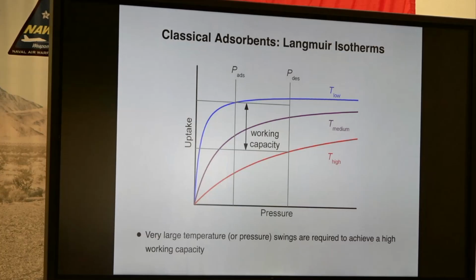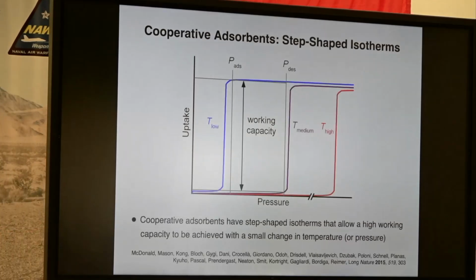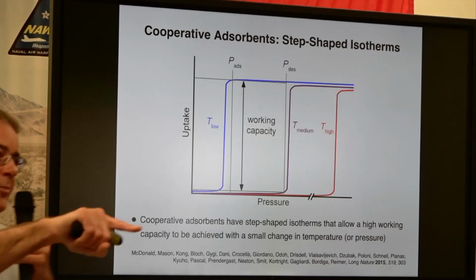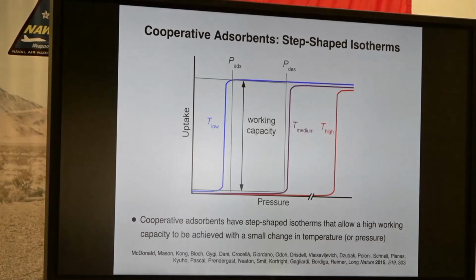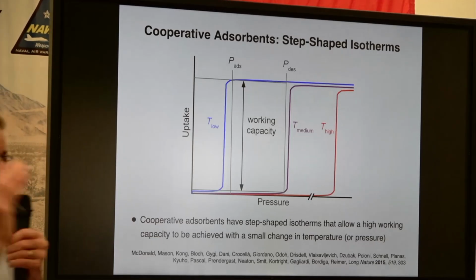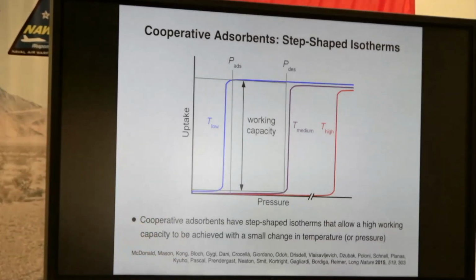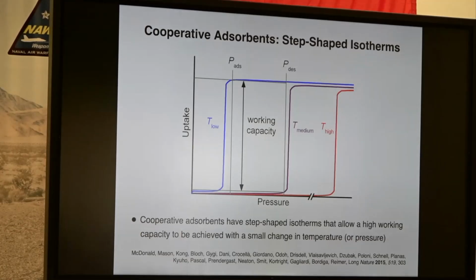And so if you were just trying to think about the response to a gas pressure, what I would like to have for an efficient separation, you would not come up with this Langmuir isotherm that almost all porous solids show. You might instead come up with something that looks like this, where you have a sharp step, a sudden transition at a particular pressure and temperature. You go from no uptake of the molecules to filling your material with the molecules. This vertical switch-like response is due to some cooperative adsorption behavior. And so you can create step-shaped adsorption isotherms in materials in a variety of ways, but we want to do it in a chemically selective way. And the advantage of this will be, if you have that sharp step, you can swing between fully loaded with molecules and fully unloaded with either a small pressure change or a modest temperature increase.